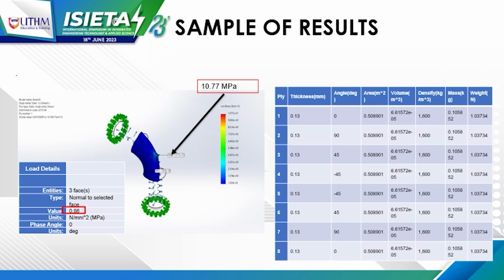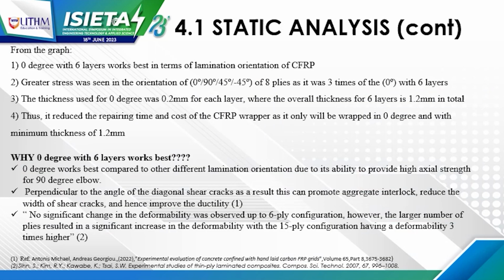Internal pressure load. What we got from this graph is that 0 degree with 6 layers works best in terms of lamination orientation. The greatest stress was seen at the 0, 90, 45, -45 of 8 plies. So it can reduce the repairing time and cost of the CFRP wrap, as it only needs to be wrapped in 0 degree with a minimum thickness of 1.2 mm. From this simulation, we can know which one is the best and which is the optimum thickness.